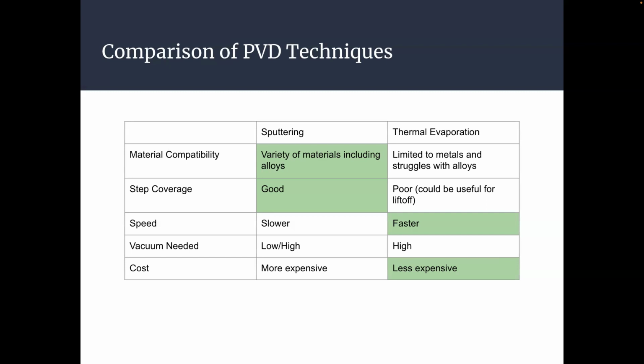And if we remember the mean free path concept, particles in a lower pressure environment have longer mean free paths. So for sputtering, with the higher pressure environment, they'll have shorter mean free paths. They'll bump into more particles along the way before reaching the surface, so they'll naturally come from more angles, versus thermal evaporation, where they just come straight from the target. Thermal evaporation is usually faster, versus sputtering, which is slower. The cost is also more for sputtering, and usually the systems are simpler and less expensive for thermal evaporation.